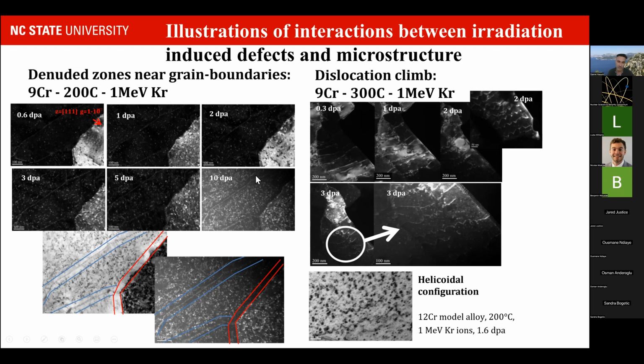When you look at this martensite structure, you have laths, and what we can see is that through irradiation, you have an accumulation of defects. The defects grow larger and more numerous. But if you look very close to the grain boundaries, you have what we call a denuded zone. The evidence is that around the grain boundary, the material seems deprived or denuded of defects. It's not because they're not forming there, it's because the grain boundary is effectively absorbing them.